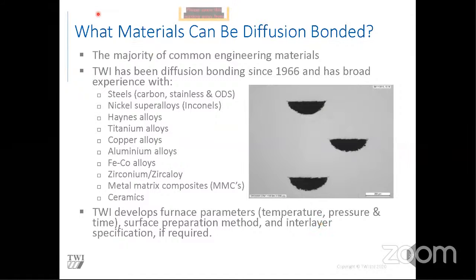So what materials can be diffusion bonded? Well, luckily for us, most common engineering materials can be diffusion bonded. And at TWI, we have looked at most materials. We've actually been diffusion bonding since 1966. And we've looked at all different types of ferrous alloys, so carbon steels, stainless steels, ODS, nickel alloys, such as Inconels, the more exotic nickel-based and cobalt-based alloys, such as Haynes alloys, titanium alloys, copper alloys, aluminium, and also zircaloy and zirconium. And we've also investigated ceramic materials and metal matrix composites. What we generally do is develop the furnace parameters and the surface preparation requirements, which I'll go into more in the next slide.